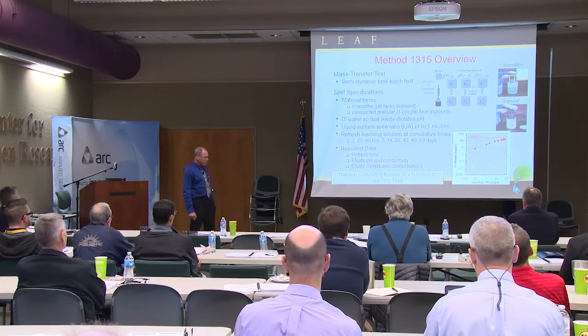The second test was Method 1315. This was developed as a mass transfer test, a semi-dynamic tank leaching test, where you take the same material and extract it multiple times in increasing time domains, maintaining the boundary condition as dilute so that you maximize the release, which is constrained by the rate of diffusion or reaction at the surface and internal to the waste form being tested, although it can also be applied to compacted granular materials as well. So this was developed learning the lessons from ANSI 16.1, etc., moving forward.